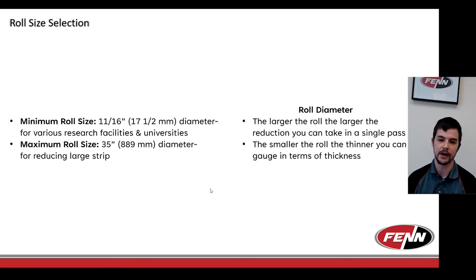On the opposite side, how thin you can roll is also gauged based on your roll diameter. Pressure is key for gauging thin. A smaller roll has a smaller amount of contact surface, which means you need less force to exert the same pressure. So the typical rule of thumb is about 1/1000th the diameter of the roll is usually the minimum you can gauge to. And depending on certain wires and materials, it may be a little bit more than that. It might be a little bit less than that, but that's just to give you guys a quick standpoint of where to start from.